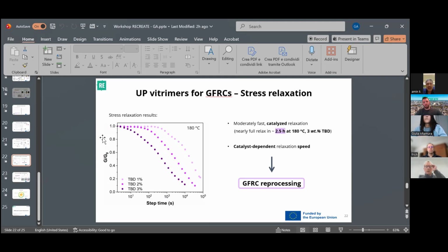What about the stiffness and the elasticity and the shock absorption after heating and cooling such a product? Is it going to change in any parameter? Yeah, actually, stiffness, we have seen that by doing multiple stress relaxation, typically we have a higher Tg, higher modulus, because we are introducing some irreversibility inside the system, because a side reaction occurs, and for example, instead of creating ester and hydroxyl, some ethers form, and ethers are irreversible. So typically we get an improvement because the Tg gets higher. So we have a bigger glassy plateau, and yeah, better performance in that term. I don't have any data about shock resistance, but in general, when we do this thermal treatment, we heat it up slowly and we cool it down slowly. So from the thermal point of view, that shouldn't be a problem. All right. Thank you very much. Thank you.